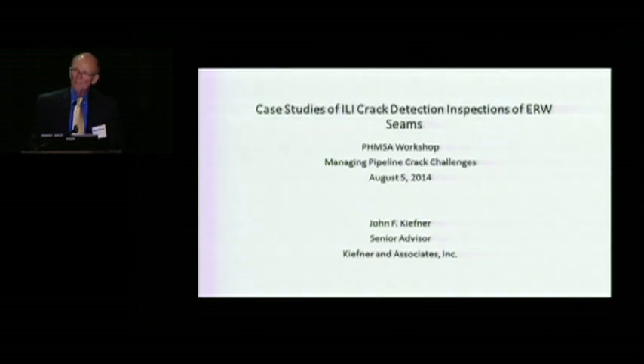The presentation I have is on crack detection case studies that we looked at as part of a study sponsored by PHMSA. Since there is sort of a negative connotation to some of the things you're going to see, I don't want to give the impression that this is somehow against inline inspection. Let me put it in perspective this way. When you're all sitting around doing your integrity management for corrosion, if your pipeline is piggable, nobody pops up and says, let's use a hydrostatic test. The reason is because you have confidence in the corrosion tools. That's where we need to get to with the crack tools.